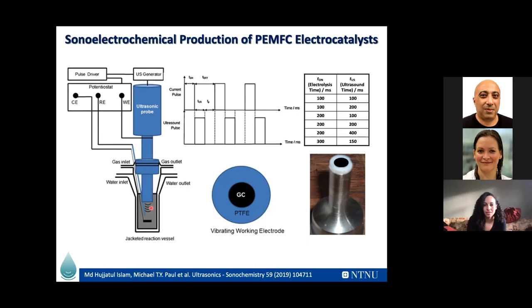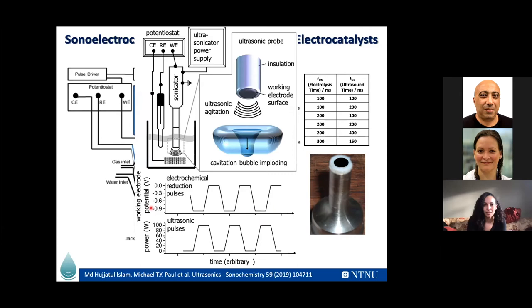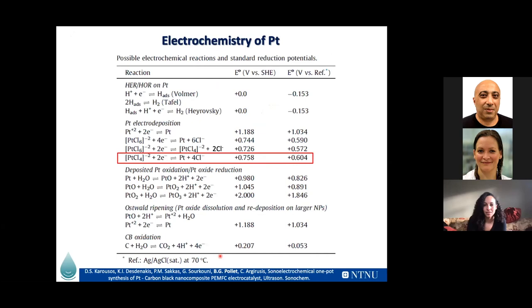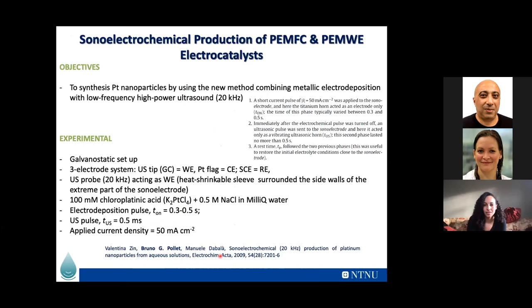Okay, now this is also a bit of an up-to-date diagram, but we looked at these electrochemical reduction pulses and ultrasonic pulses in order to get the nanoparticles that we wanted. We focused pretty much on the chloroplatinic acid here, the reduction at this potential, at this reaction here. I don't want to go through the details, but when I send you the PDF, I will leave them in there for those who want to repeat those experiments.